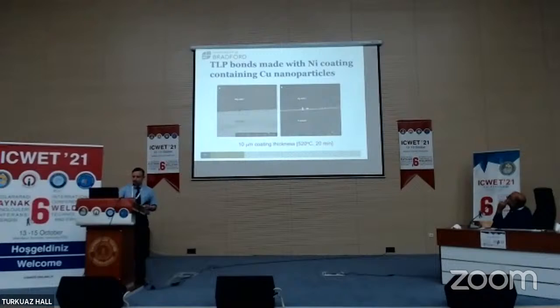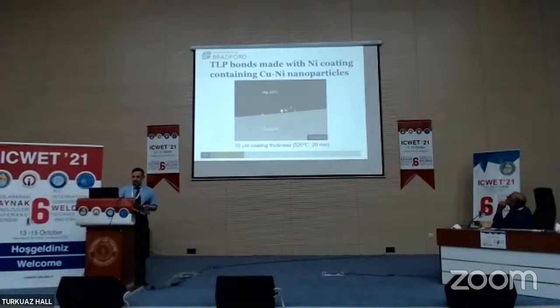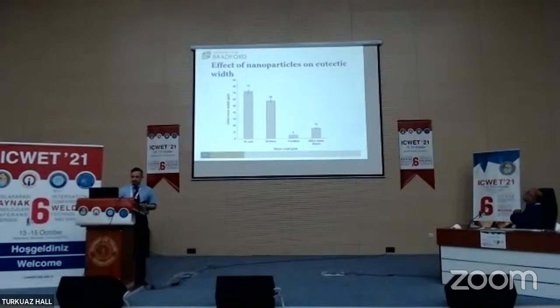And this is an example with copper nanoparticles. And this again is another micrograph showing what happens if we use a mixture of copper and nickel nanoparticles. So not a coating, not a solid interlayer, but a mixture of copper nickel particles. So the measurements of the eutectic widths are shown in this diagram. So joint zone width, showing the eutectic width as a function of the nano coating type. So the lowest eutectic width formed is for our mixtures, nickel and copper nanoparticles.